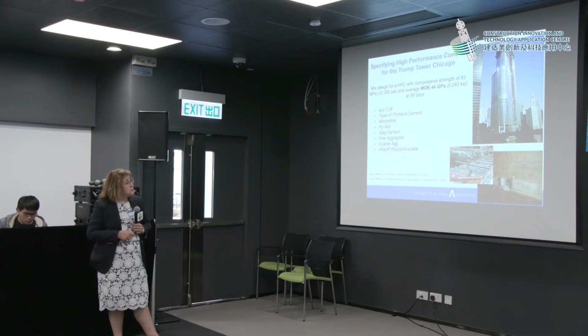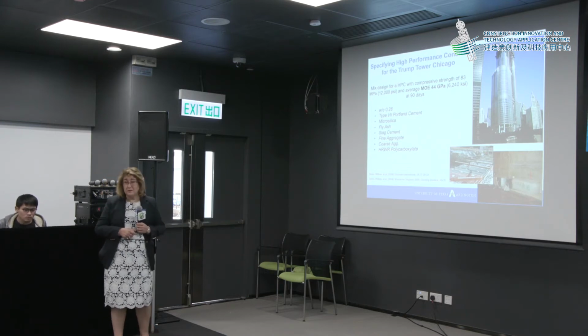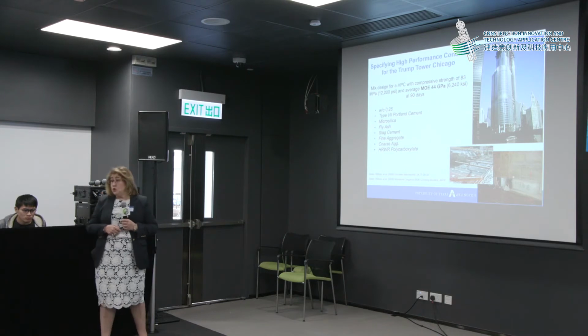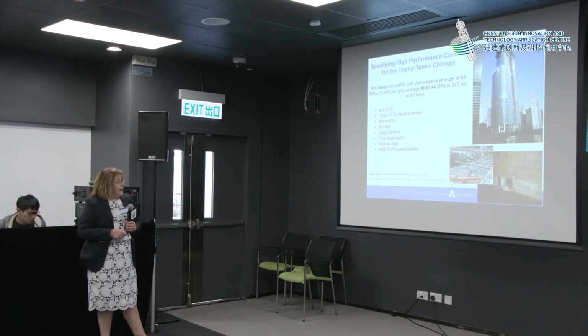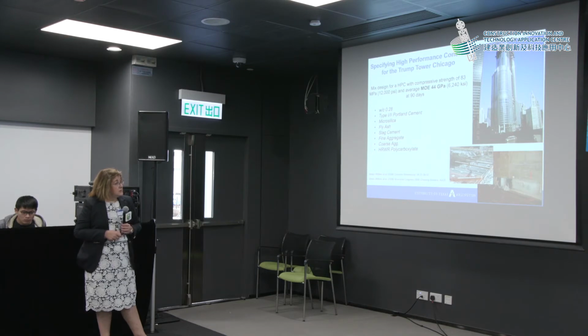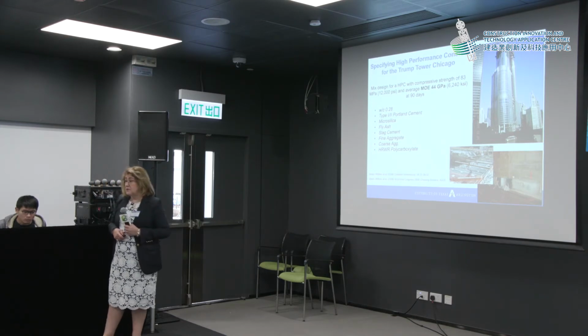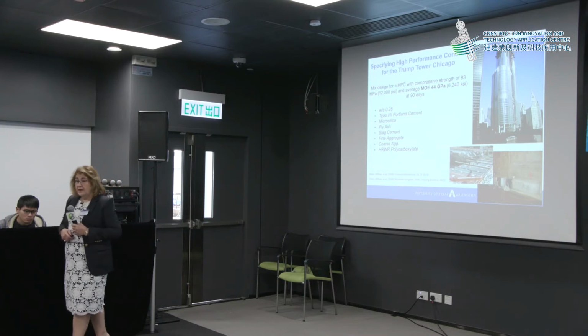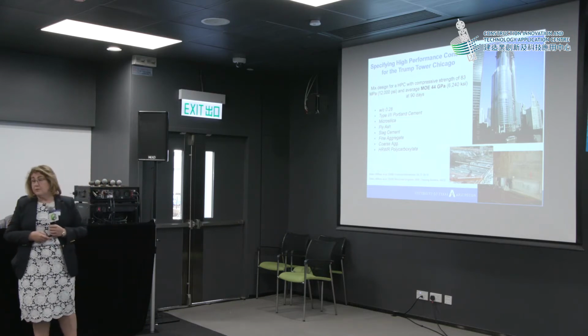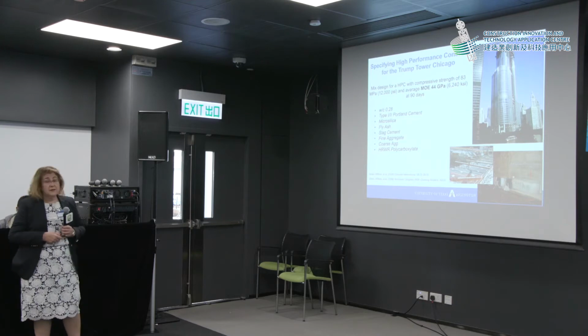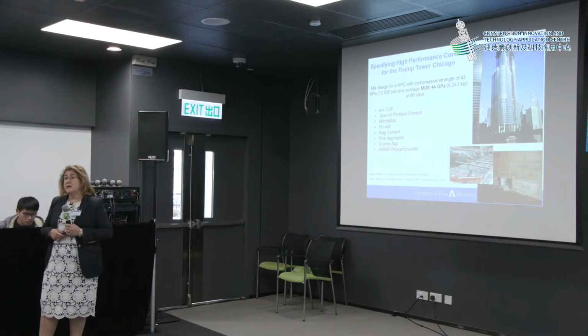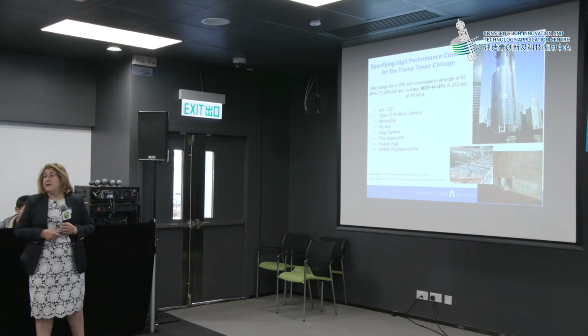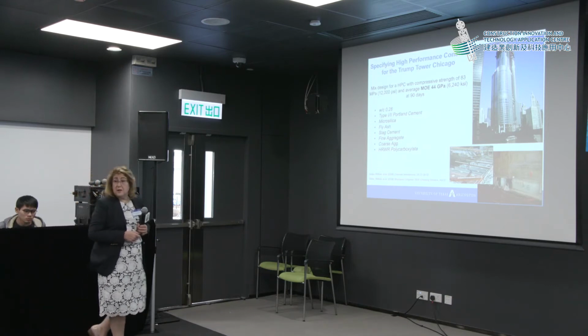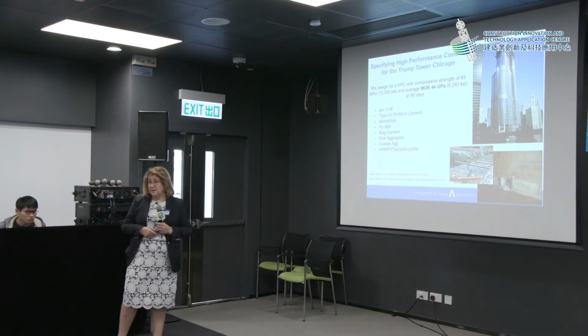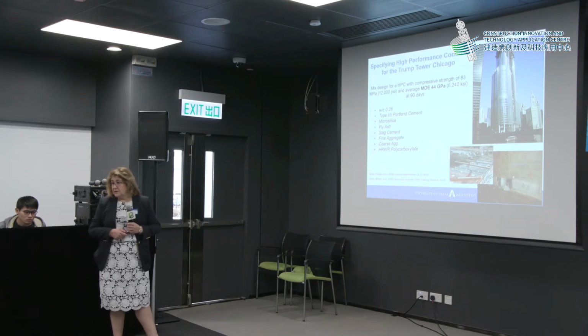So in order to do that, actually it was Prairie who designed the concrete, used a water to cement ratio of 0.28, too low. Microsilica, fly ash, slag, fine aggregates, coarse aggregates, but everything was local in Chicago. Now, for the Kingdom Tower, the problem was that 0.28 was not even pumpable at the 1 kilometer height that the Kingdom Tower is about to go.